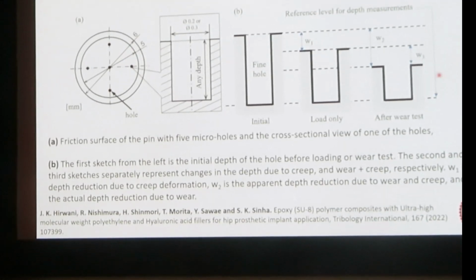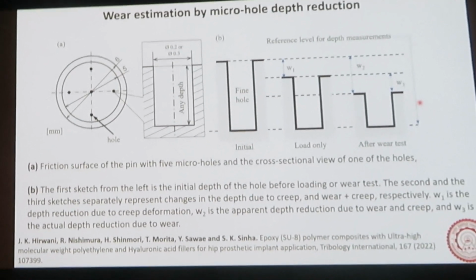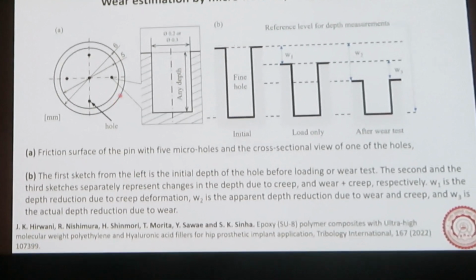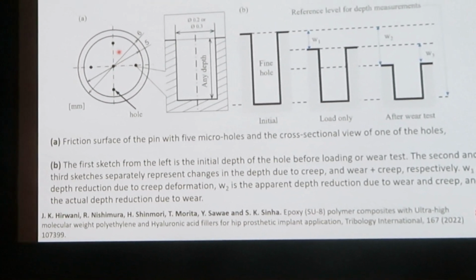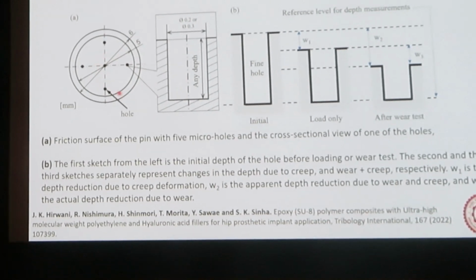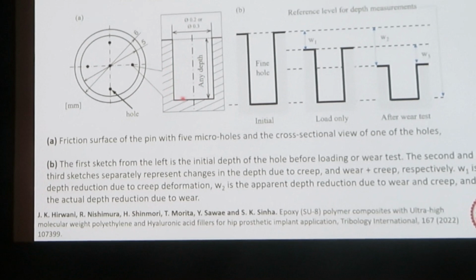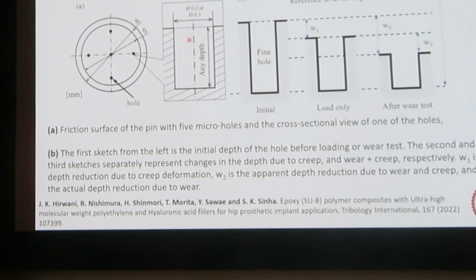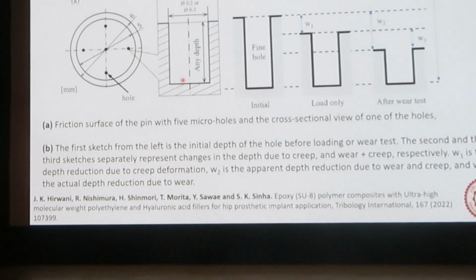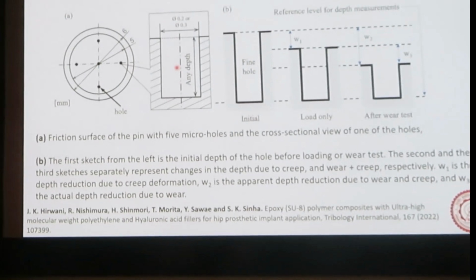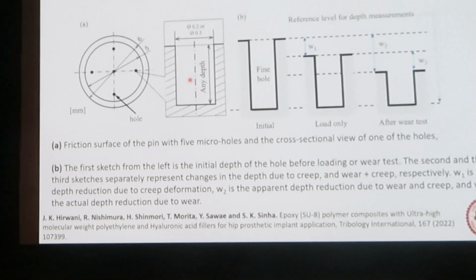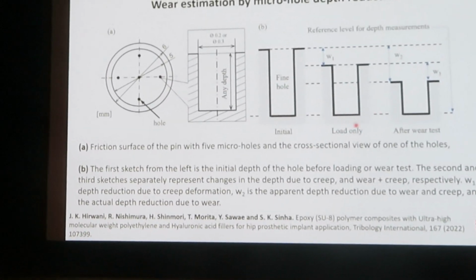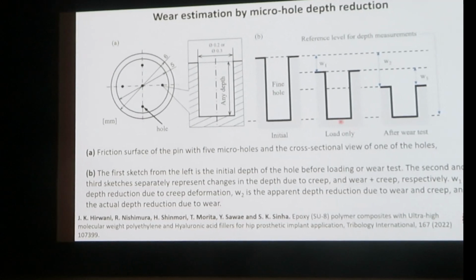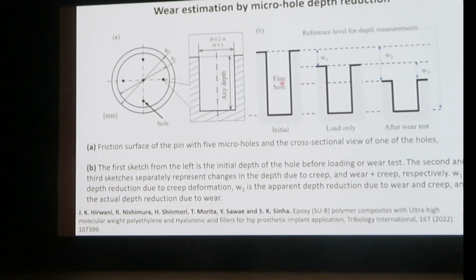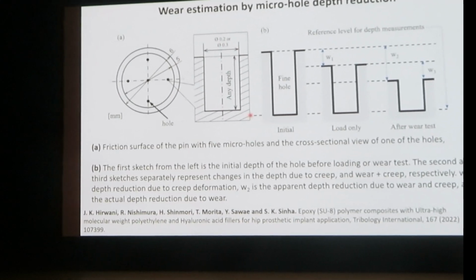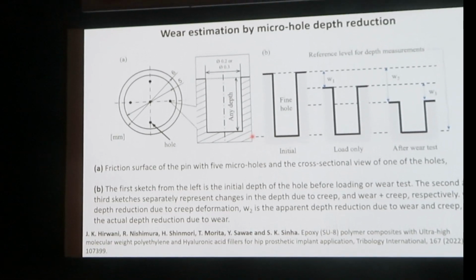So that's why it is quite complicated. In this work we innovated by making micro holes on the specimen itself, and this part of the work was done at Kyushu University here. So you have a certain depth, and as the specimen wears out, the depth will reduce. By measuring the depth, you can find out the wear loss, and this is how we did it. Of course, we removed the depth loss because of creep, because as long as the material is under stress, there is creep also. So finally this method gave us a way to find out wear loss without going through the mass loss method.